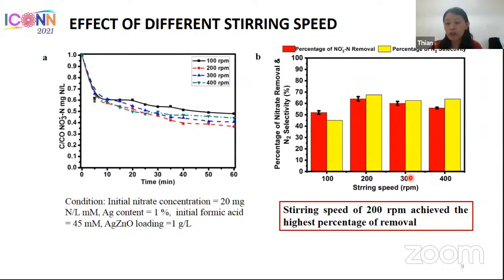But if we keep on increasing the stirring speed, it will not enhance the percentage of removal, because we did observe there is a vortex in the middle of the colloid solution, and it resulted in non-homogeneity in the solution.